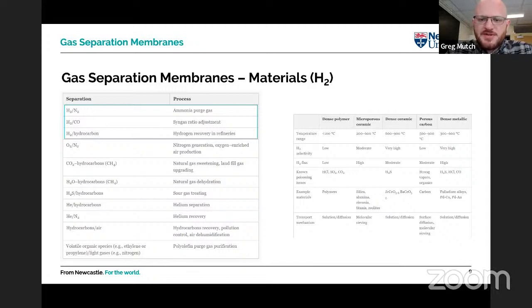If I pick the first example here, which is hydrogen production, or hydrogen separation, I just wanted to talk about the different classes of materials, the different potential applications and the different properties of these materials. So we can use dense polymer membranes. This is essentially just a non-porous piece of rubber, almost like the wall of a tire. Microporous ceramics, so ceramic materials with very small porosity. We can use dense ceramics, so they don't need to have porosity. We can get gas transport through ion conductors, so potentially oxygen ion conductors or proton conductors. We can use porous carbon materials. We can use dense metallic membranes. These are probably the most famous or most popular membranes for hydrogen production, palladium-based membranes, where hydrogen adsorbs on the surface, separates into protons and transports through the solid metal.